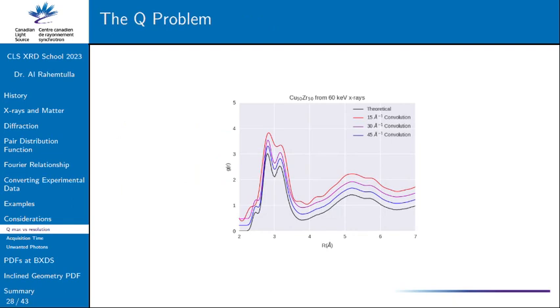So in terms of going far out into Q, we kind of saw a little bit of these things. An example here is just even with an amorphous material. If I adjust how far out into Q we go for something amorphous, even when we have broad peaks, we can start over-broadening nearest neighbor interactions just because we're not getting that damping sinc function to go far enough out. So we get artificial broadening.